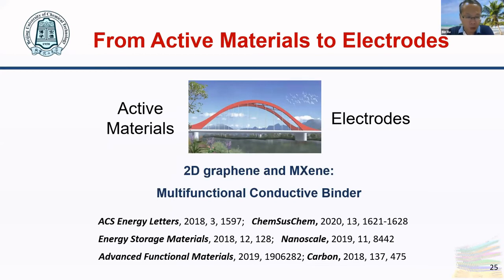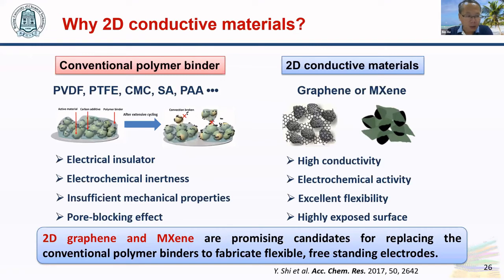Here, we proposed a new strategy using 2D materials like graphene and MXene as a multifunctional conductive binder to construct electrodes for batteries and supercapacitors. For example, porous carbon electrodes are usually prepared by coating the slurry of porous carbon, conductive additive, and also the polymer binder such as PVDF, PTFE, CMC, etc.